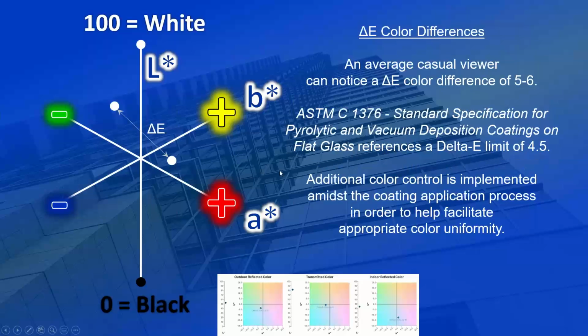An average casual viewer can notice a delta E color difference of around 5 to 6. ASTM limits the installed delta E of an IGU to a limit of 4.5. Internally, Guardian aims for much tighter tolerances than these. And for many of us in the architectural industry, we're looking at colors, buildings, and samples on a regular basis. We can probably see delta E's tighter than 5 to 6. And if you have two samples side by side at the far end of that allowed delta E, you could also probably see a difference.